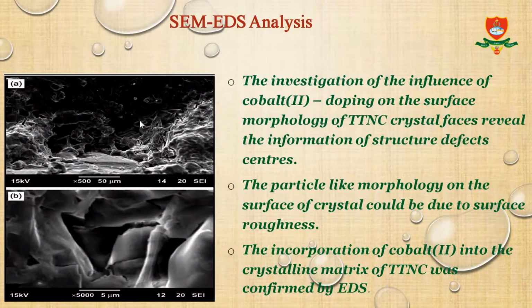SEM-EDS analysis. The investigation of the influence of cobalt-2 doping on the surface morphology of TTNC crystal faces reveal information on structural defect centers. The particle-like morphology on the surface of the crystal could be due to surface roughness. The incorporation of cobalt-2 into the crystalline matrix of TTNC was confirmed by EDS.